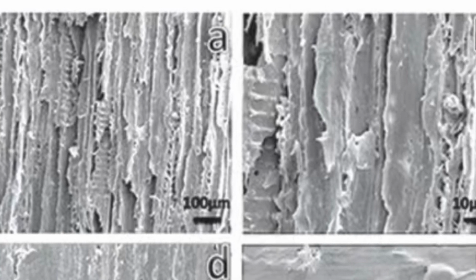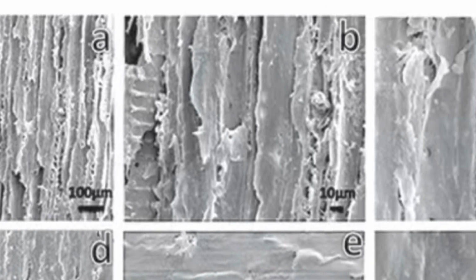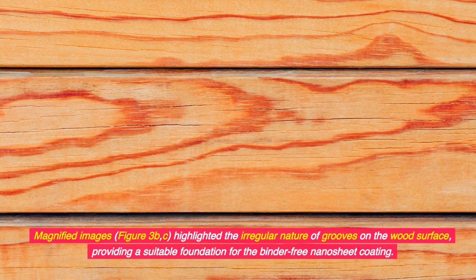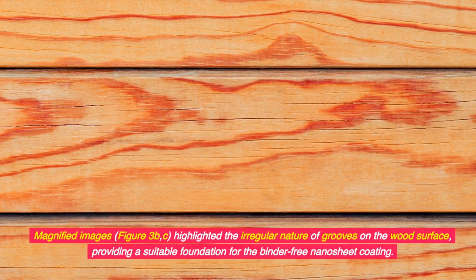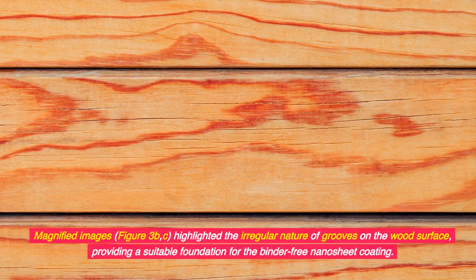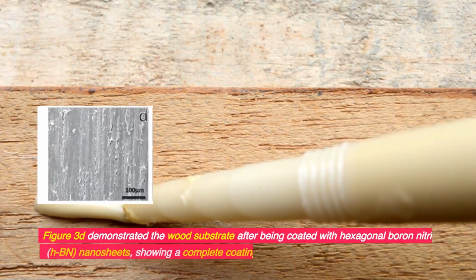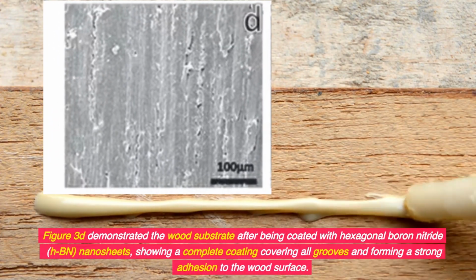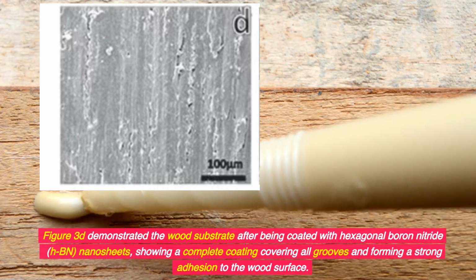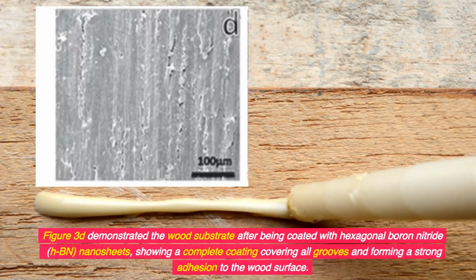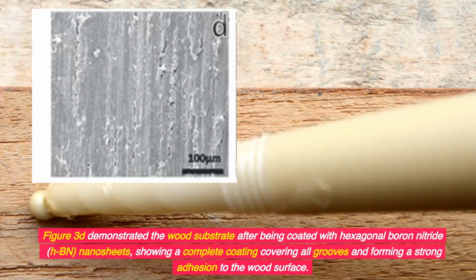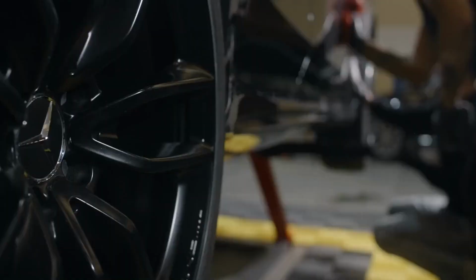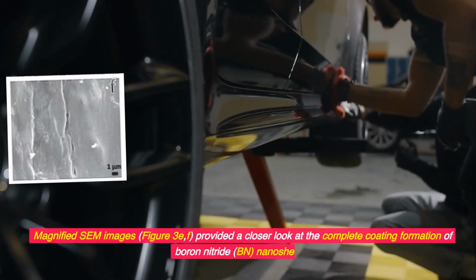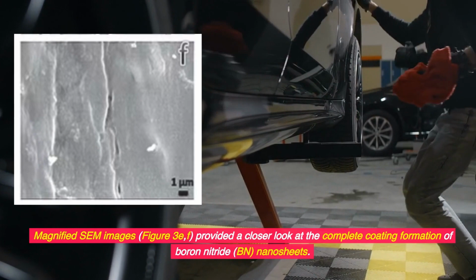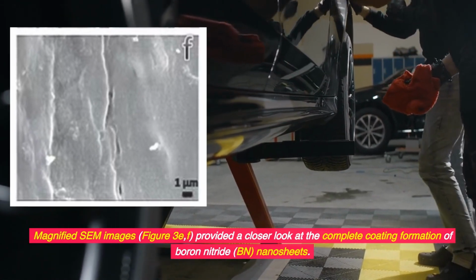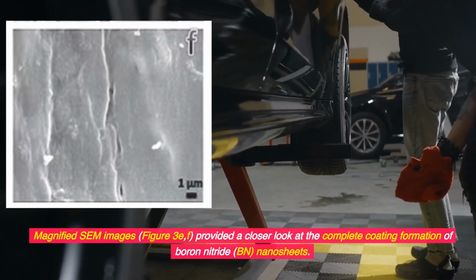Magnified images, Figure 3B-C, highlighted the irregular nature of grooves on the wood surface, providing a suitable foundation for the binder-free nanosheet coating. Figure 3D demonstrated the wood substrate after being coated with hexagonal boron nitride (HBN) nanosheets, showing a complete coating covering all grooves and forming a strong adhesion to the wood surface. Magnified SEM images, Figure 3E-F, provided a closer look at the complete coating formation of BN nanosheets.